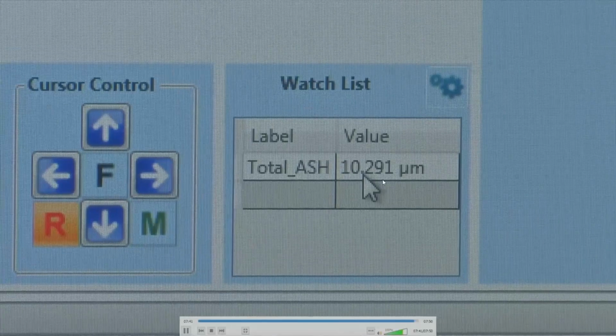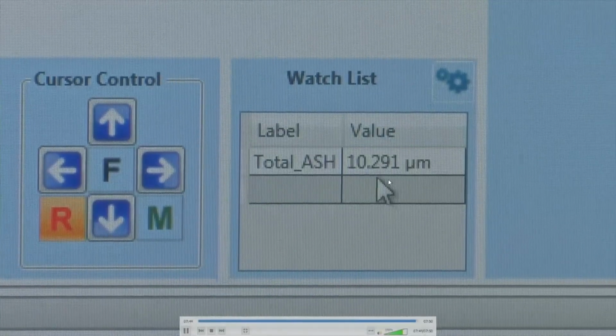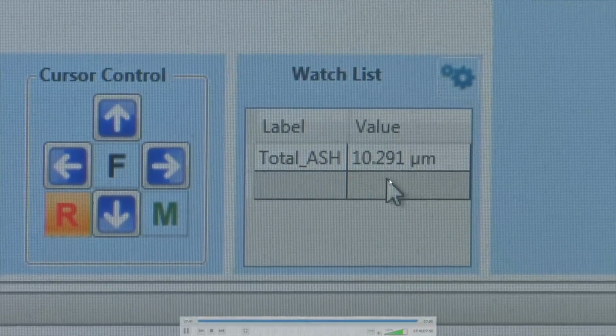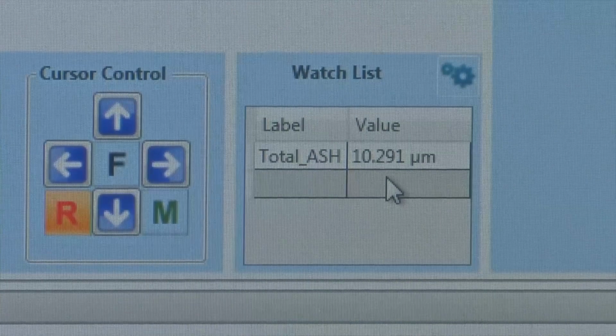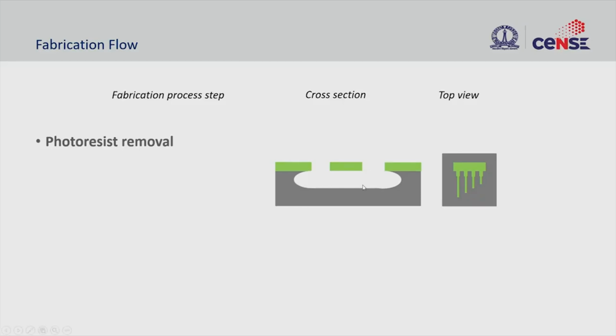if you can see here, the topography is about 10.291 micrometers. So we have etched approximately 200 nanometers of nitride, and we have etched nearly 10 microns of silicon. So after all this process, this is what we have been measuring. So what we measured was this height, right? And this height was 10.291 micrometers, right? And this is a demonstration of how we fabricate this cantilever.